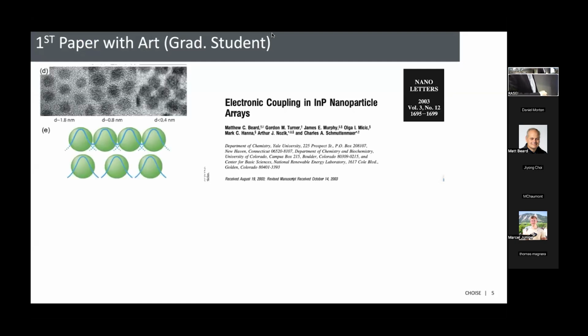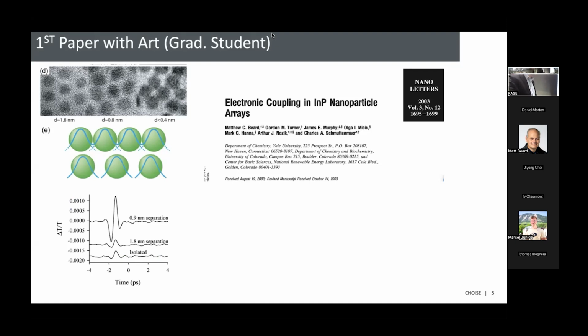So we did that. Art and Olga had actually published a paper a year before showing some effects on the optical spectra when they made these nanocrystals closer and closer together. And so we did this experiment using time-resolved terahertz spectroscopy, and you could see when they get closer, you get a big signal because the carriers start to delocalize over many nanocrystals and so forth. So that was great. It started us off here.